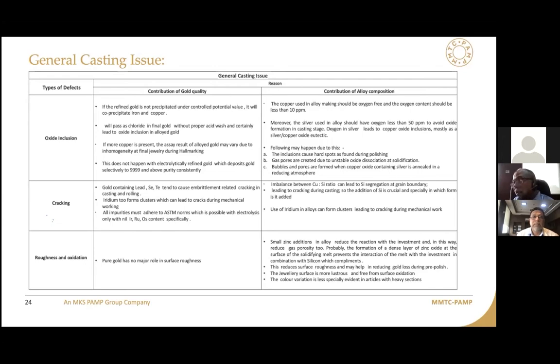Now, cracking. If your gold is containing lead or selenium or tellurium, it will form embrittlement, and this embrittlement will lead to cracking, and you can get cracking during rolling or your casting. So all elements must conform to ASTM. Again, in cracking from the alloy, the copper silicon ratio, which I mentioned, is very important. Otherwise, it will form coarser grains and orange peel effect, graining, all these things,